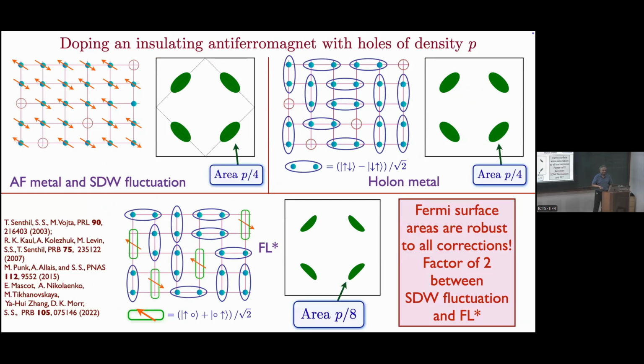So to summarize, the antiferromagnetic metal gives you p over 4, the holon metals give you p over 4, and the FL* gives you p over 8. And all these areas are very robust. I've just presented very simple cartoon pictures, but the answers are exact. There are no corrections in any of these 3 states to these values. So that's the remarkable thing.